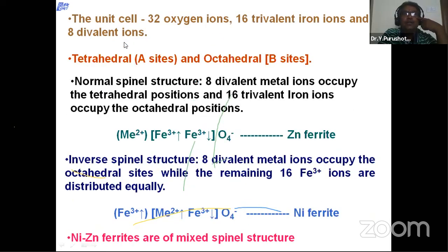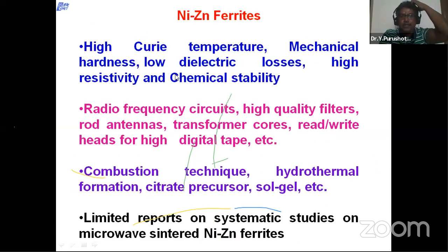So the unit cell of the ferrites contains 32 oxygen ions, 16 trivalent iron ions, and 8 divalent ions. Depending upon the distribution of these, whether it is a spinel ferrite or an inverse spinel ferrite, and particularly nickel zinc ferrite has a lot of applications as transformer cores. You see, radio frequency circuits, high quality filters, rod antennas, transformer cores, read-write heads for high digital tape, etc.